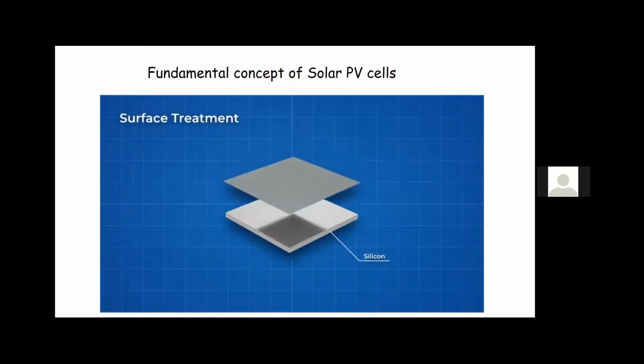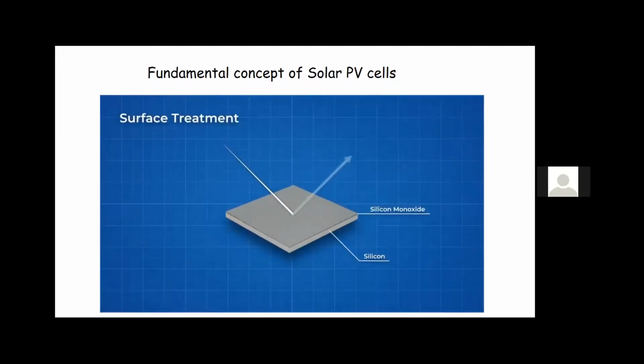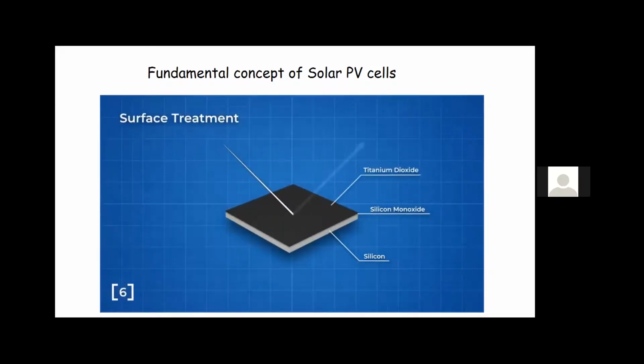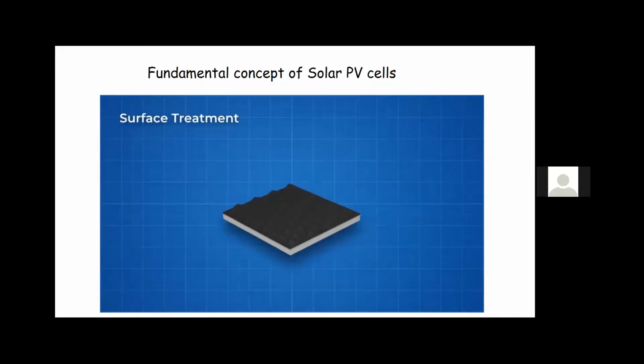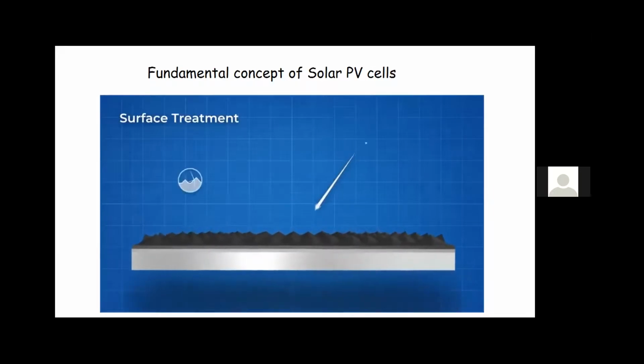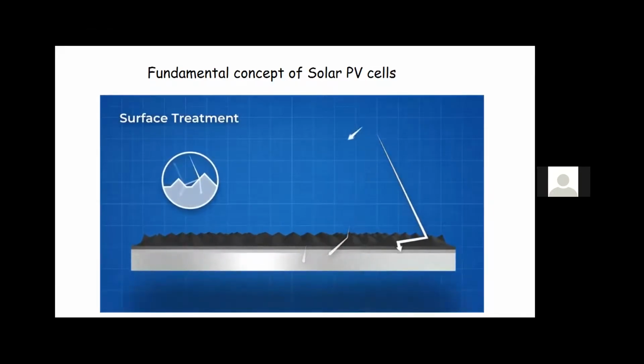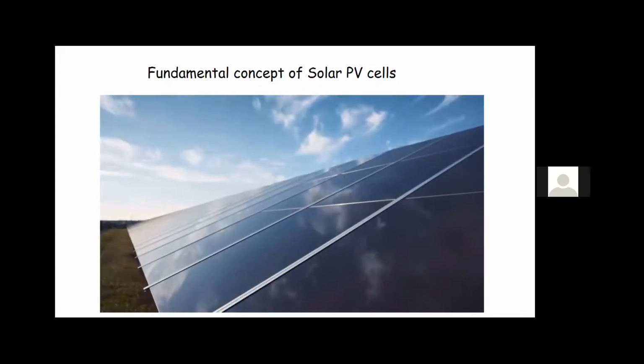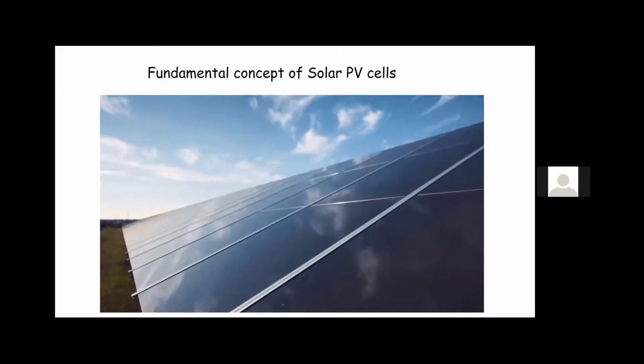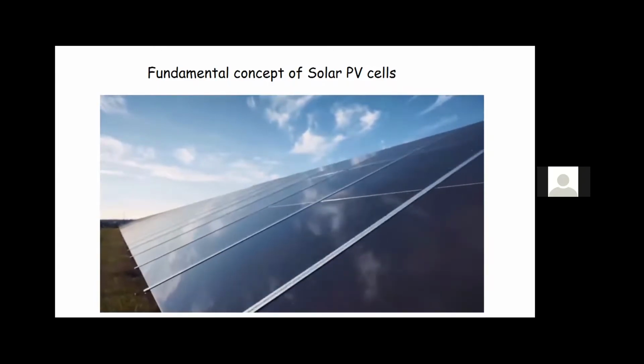For this reason, silicon is often treated with a layer of silicon monoxide which can reduce the light reflected to just 10%, while a second layer with a secondary material like titanium dioxide can reduce it as low as 3%. Texturing the surface of the material can further increase the probability of light being absorbed. If it is textured like this, light that is initially reflected has another chance to strike the material and be absorbed. Only light that is absorbed can potentially cause the photovoltaic effect, but not all light will.